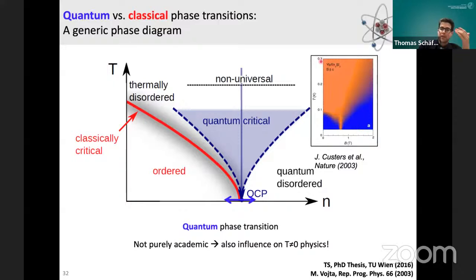where they measured the electrical resistivity and drew this phase diagram where they shaded the regions where the temperature dependence of the electrical resistivity is T squared in blue. So the T squared is the usual Fermi liquid behavior, which you would expect from the resistivity of a Fermi liquid, whereas the red shaded region indicates the so-called strange metallic phase, which is described by a linear T dependence of the resistivity. So you see that this existence of a quantum critical point also shows up at finite temperatures.